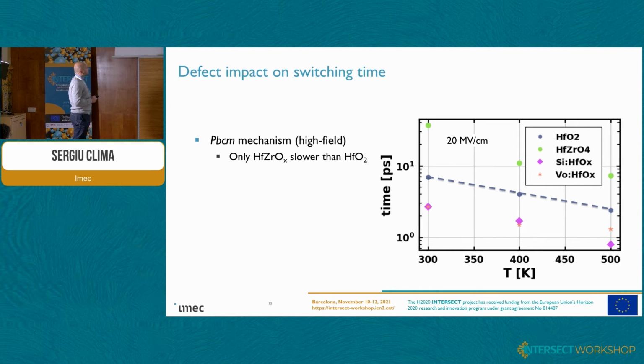It's interesting to see that, as we expected from the nudged elastic band calculations before, the oxygen vacancy or silicon doping break the symmetry in the system. Therefore the switching occurs in small steps, not all oxygens at once as you saw in the animations before, but one oxygen after another. We have faster switching when we have defects.